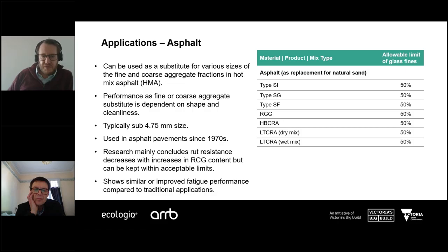And again, research has shown that rut resistance tends to decrease with increasing recycled crushed glass content, but can be kept within acceptable limits. It's been shown that up to 15% recycled crushed glass content, we don't have any concerns with rutting resistance, but as we increase significantly above that, there's the potential for a reduction in the rutting resistance, and most of that is related to the surface texture of our recycled crushed glass, which tends to be a bit smoother than the natural aggregates that it would be replacing.